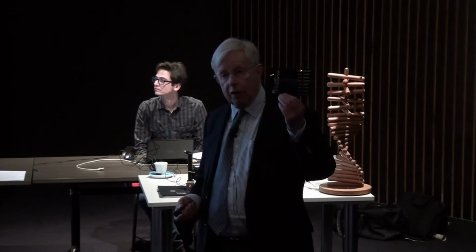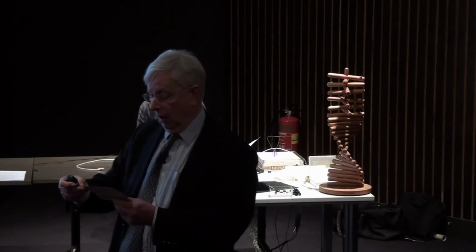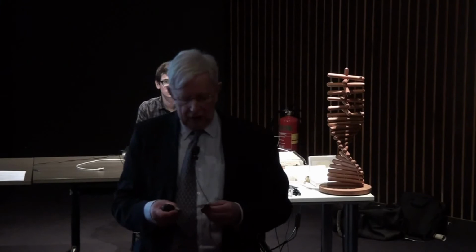The only downside of these liquid crystal thermometers is that blue is hot and red is cold. That is because the pitch of the helix gets shorter as you cool it down, and the other way around, is that right? Yeah, the other way around. But you can get materials that work the other way. So I can pass that round.